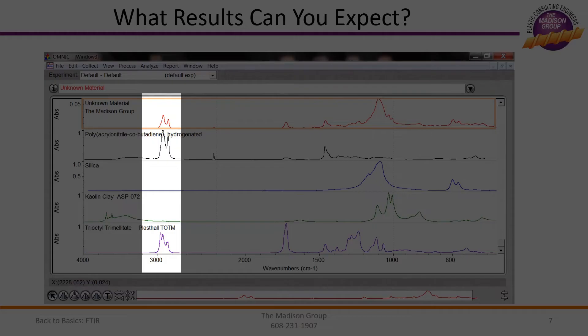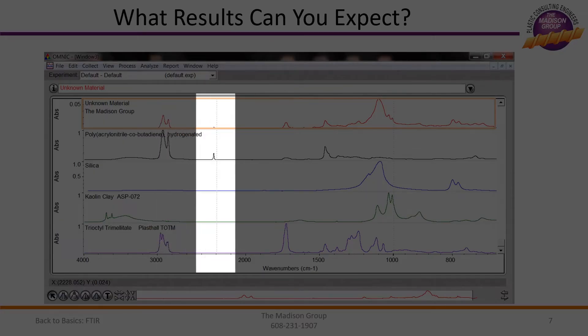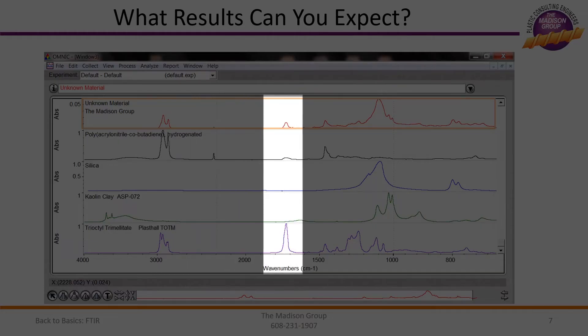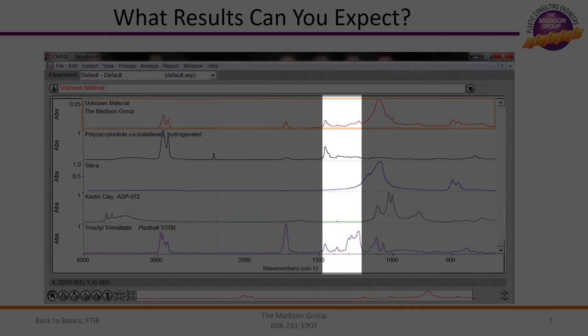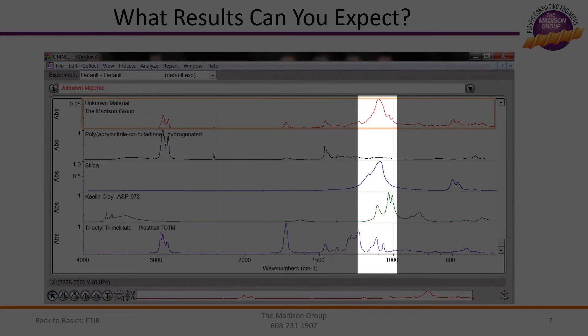As we can see, this region contains absorptions that are from the base polymer and the plasticizer. Between 2200 and 2300 wavenumbers, we have a peak that is associated with the base polymer. Next, we have overlapping signals from the polymer and plasticizer. And finally, we see broad absorption bands that indicate two different types of inorganic fillers. From this comparison, we can recognize that most of the peaks in the original spectrum were represented in the identification and can be confident in the results.